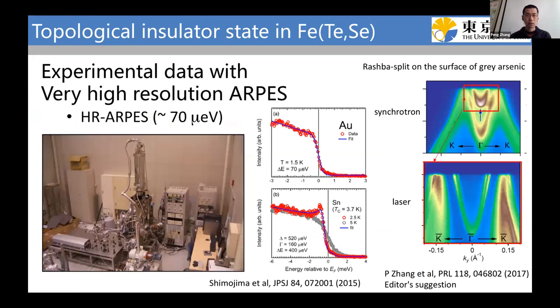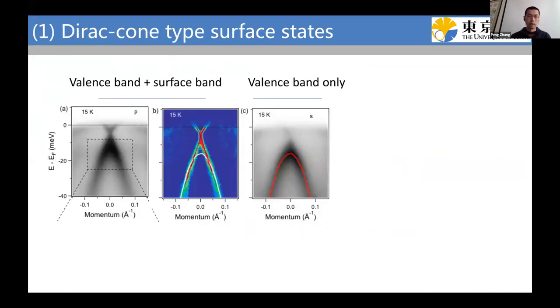In the University of Tokyo, we have a very high resolution ARPES, which can reach a resolution of less than 1 meV. With such a high resolution ARPES, we can resolve some features that cannot be resolved by a synchrotron ARPES, like for the arsenic Rashba state. So we used this system to study this iron tellurium selenium. We directly resolved Dirac cone band structure